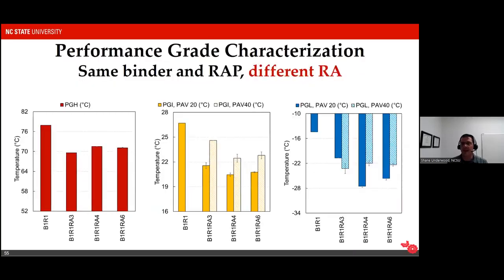So I show you this example where we have a different recycling agent. This is just a snapshot of some of the results. You can see that this bar here corresponds to the binder and the RAP itself. And as we add the recycling agents, they become softer. At high temperatures, they become softer. But if you look at the low temperature case, especially when we oxidize and age those materials, you can see that each recycling agent basically gives you the same rheological behavior.